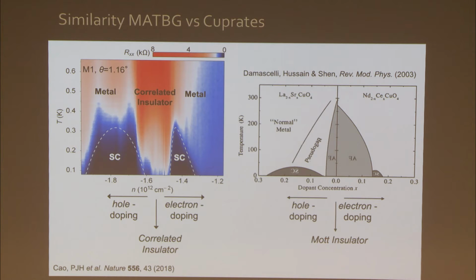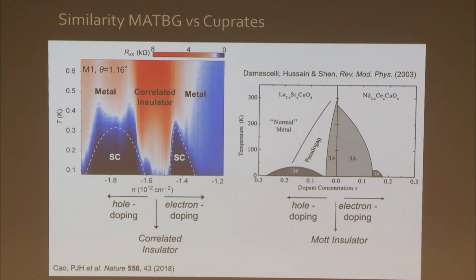In magic angle graphene, at 2 electrons or 2 holes per moire unit cell, you have a correlated insulator due to strong interactions between your electrons. And if you add a few more holes, you have a superconducting dome. If you add electrons, you have another superconducting dome. Now, the obvious similarities, there are also many differences, which I'm not mentioning, okay? So don't think that the analogy only goes so far. But one big difference between this and this is that this is actually a theoretical phase diagram. In order to populate this phase diagram with experimental data points, you need to grow thousands and thousands of crystals with different stoichiometry, often different material classes, because not all materials can be grown at all dopings. This is an experimental phase diagram, which is done in one device with a single disorder realization without chemical doping, and it takes me a few seconds to go from here to here and measure this, okay?